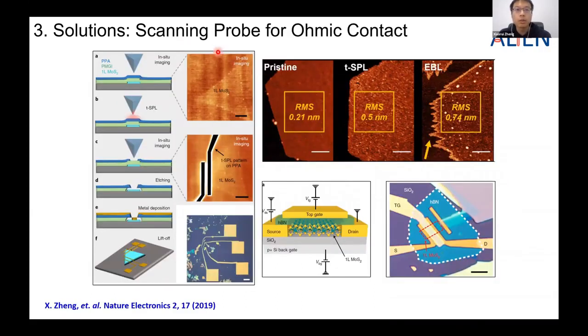Okay, so for scanning probe lithography, to improve the contact quality, we developed a multi-stack lift-off process by using the PPA and PMGI two-layer process. We are able to create, firstly, the nanostructure on the PPA layer by using the thermal tips. Then the good advantage of this process is we could image the 2D layer in situ, and then we put on the electrode by using the overlay function. This is precise and wouldn't need any markers. And more importantly, the PPA polymer can be evaporated completely without any residues.